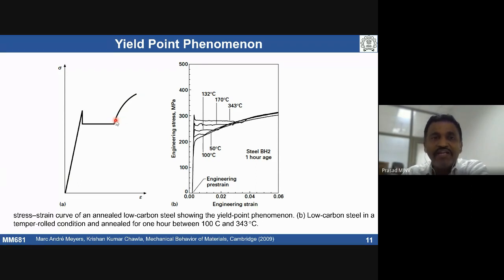When you deform material with a small amount of deformation, that can lead to formation of stretcher strains. These stretcher strains form as multiple slip bands, multiple Lüders bands, forming multiple very tiny bands. We are nucleating multiple bands so that the stretcher strain marks will be finer, and the roughness is going to be much smoother.